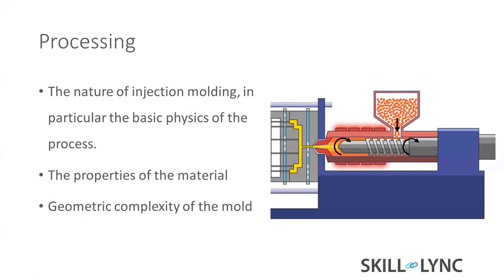We need to understand the basic physics of the injection molding machine - how the material is made ready for the shot, and how it reaches the molten state at the exact correct range. Because there are a lot of heaters, we can set the temperature. For example, polypropylene material needs 220 degrees centigrade, but we cannot keep the heater exactly at 220 because friction heat is also added. So they do trial shots to bring all the molten material to a standard, homogeneous state.